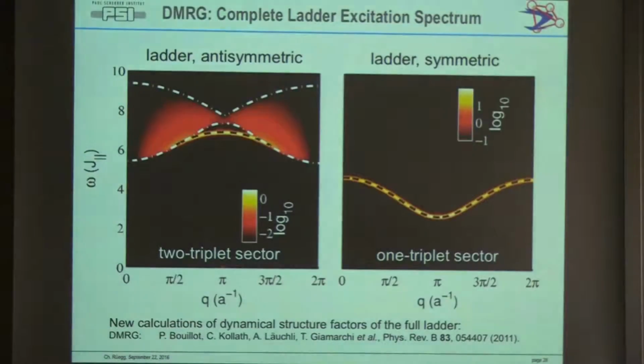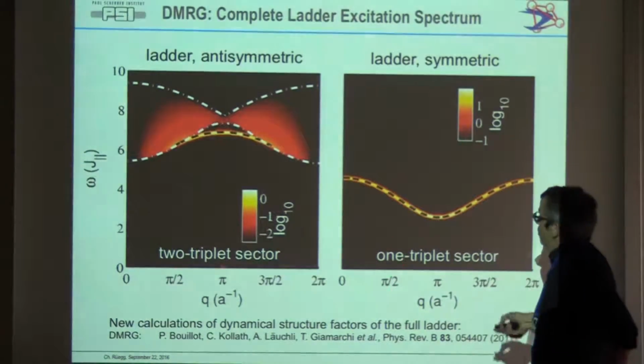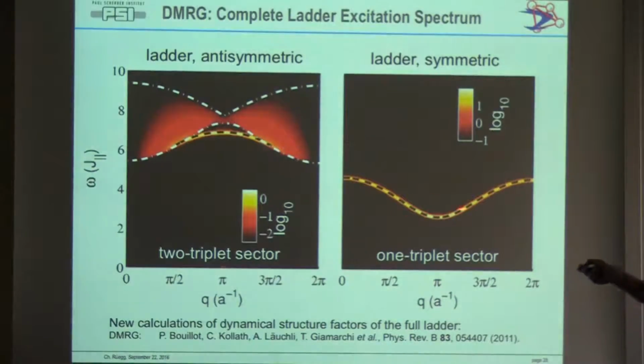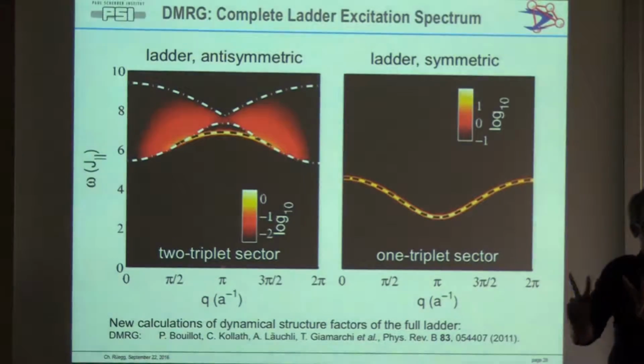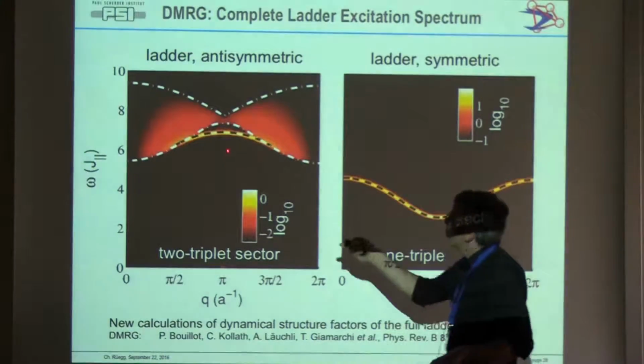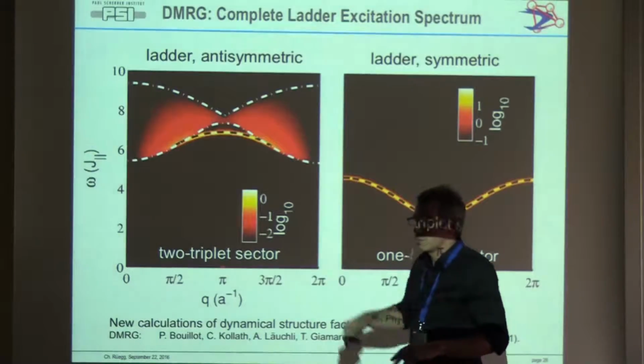So what is the excitation spectrum? This is old stuff. You can excite this triplet and it propagates in a lattice along 1D and not along the others. But that's only half of the answer. The 1 triplet excitations you see here, that's a sharp mode, exactly what I described. But there's also ways to excite 2 of these at the same time. You can do it in an incoherent way and get this kind of continuum which has a bow tie shape. If you excite 2 and they form a bound state and hop together, you gain some energy, and then you would expect a bound state to pop up here in the spectrum.